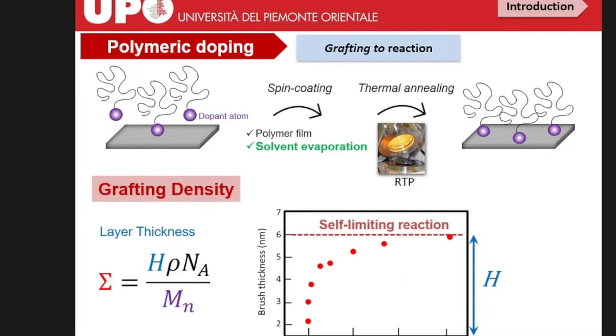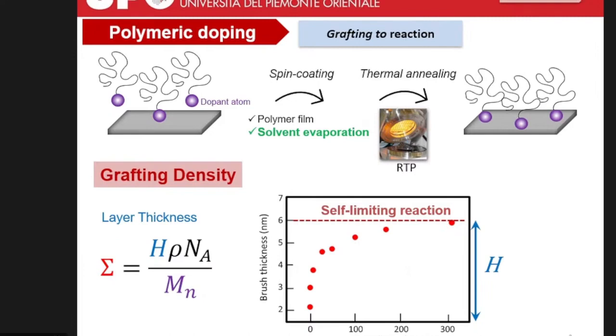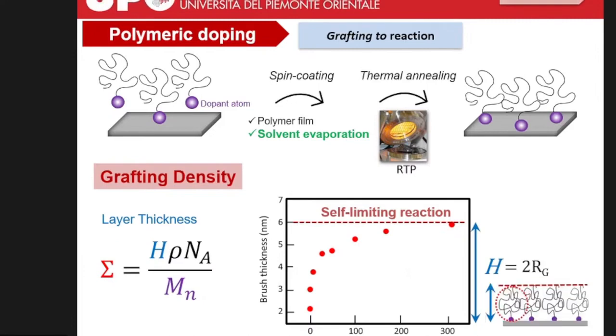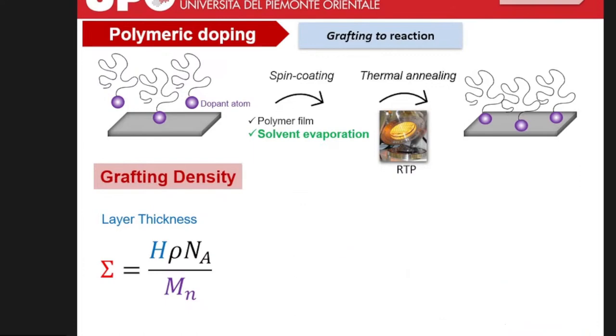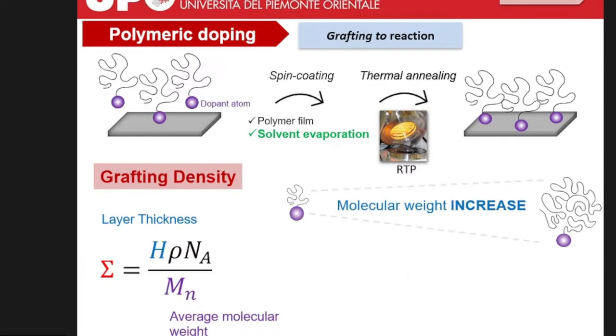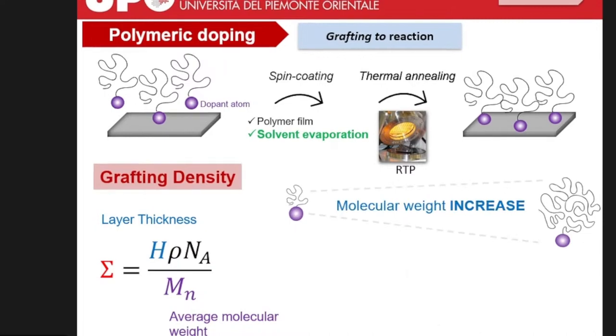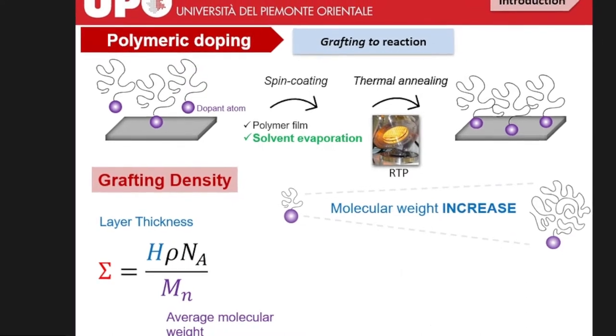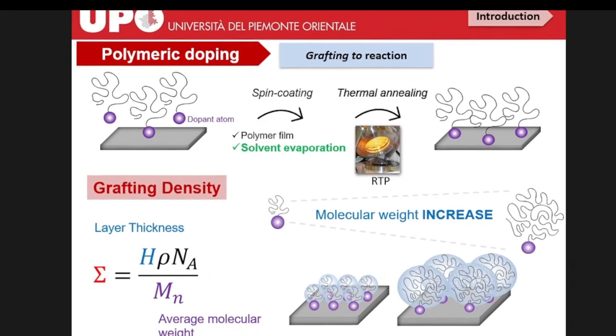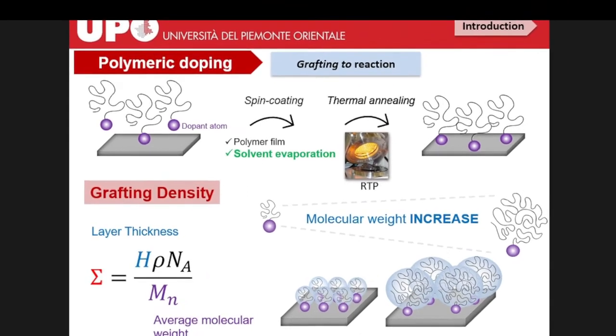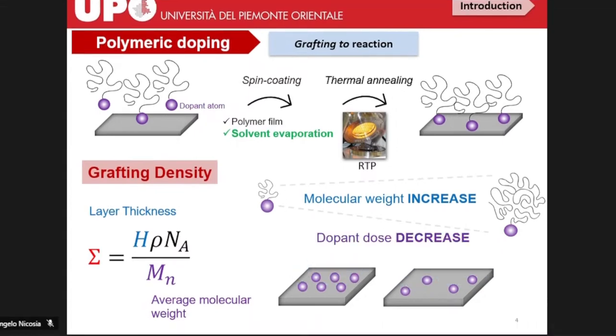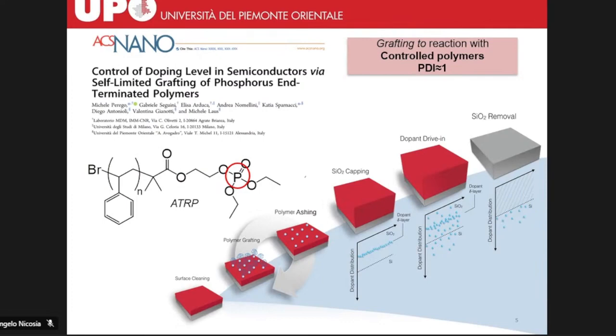And the maximum film thickness will be related to 2 times the radius of gyration of the polymer. The other parameter, the molecular weight, graphically we can see from the equation is inversely proportional, but if we compare 2 polymers, one with low molecular weight and one with high molecular weight, we will observe that in the moment the layer is formed, by steric hindrance the molecules will be organized. So increasing the molecular weight will result in a decrease of the dopant dose of atoms on the surface.